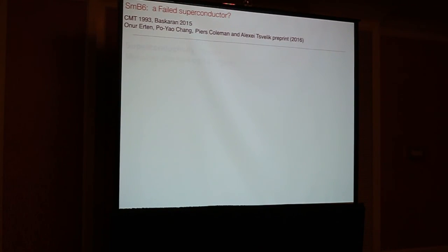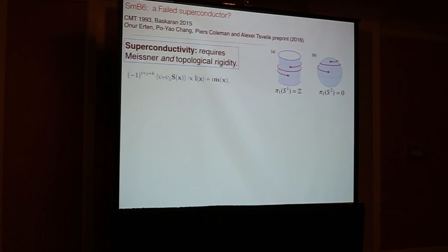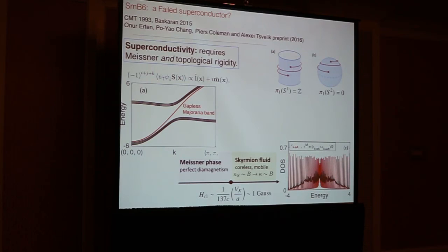And we can, sorry, I missed one thing there. And so we can actually estimate the critical magnetic field where the Meissner effect will develop. And this critical magnetic field is determined only by the Kondo temperature, the V Kondo, the lattice spacing, and the speed of light. And when you work it out, it's about 1 Gauss. So the prediction of this crazy theory is if you take samarium hexaboride and you put it in a mu metal shield, which screens out the Earth's magnetic field and can safely take you well below, 1,000 times below a Gauss, you should see a Meissner effect. Okay? That's a crazy theory.